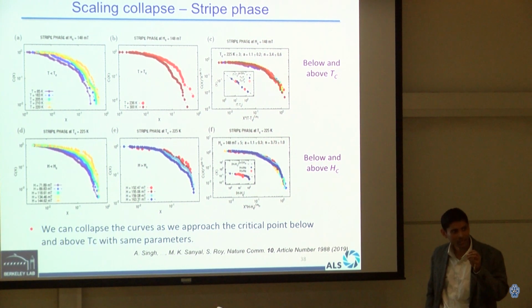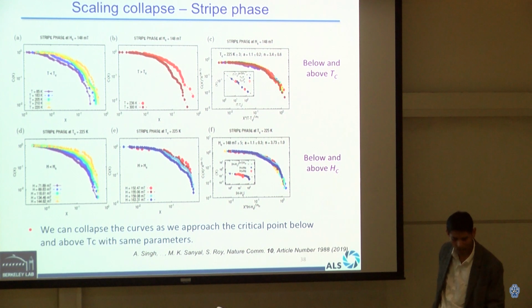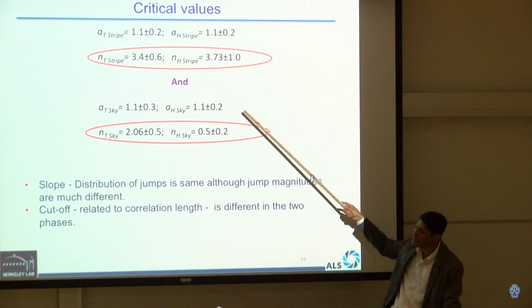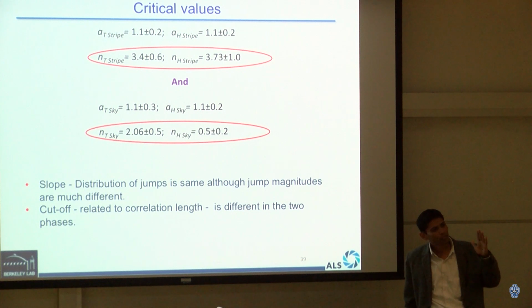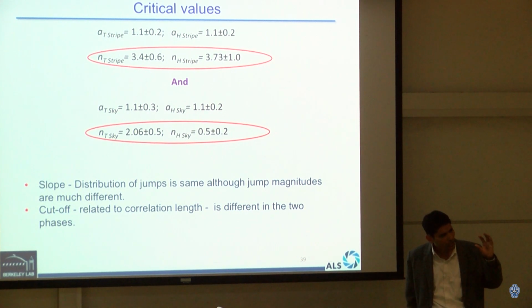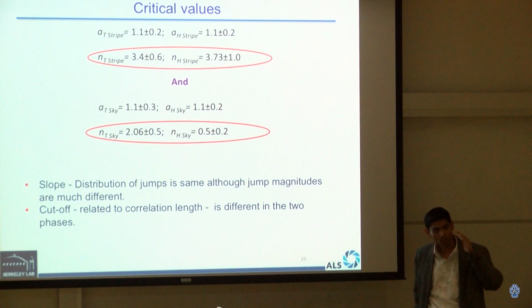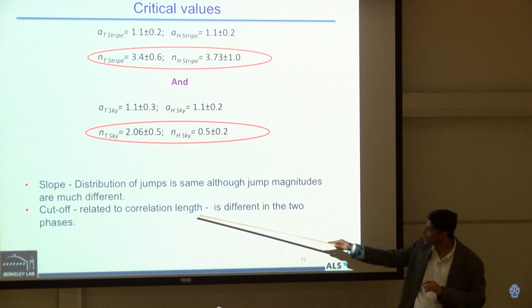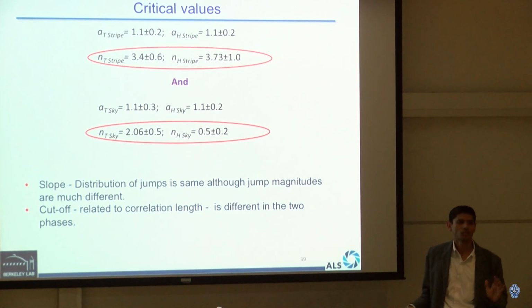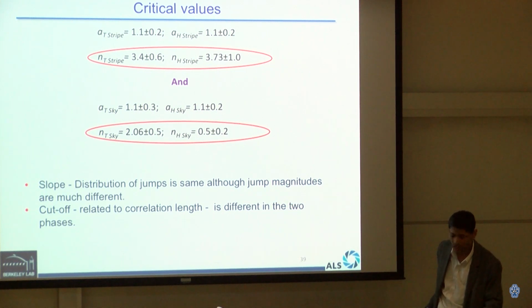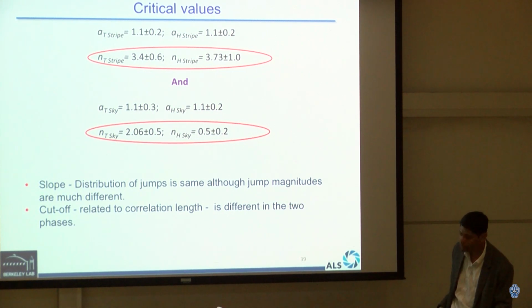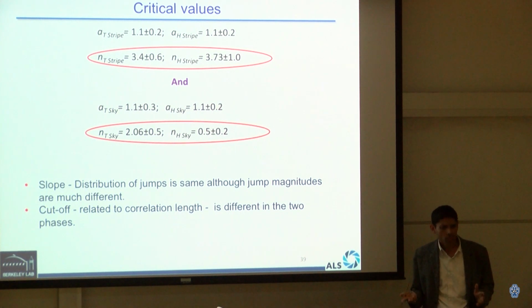From there, you can guess about the uniqueness of a phase. So we did that, and what we showed is that the slope of the skyrmion and the stripe phase are the same, meaning that although there are no jumps in the skyrmion, from a slope point of view, the distribution of the jumps, they may be small, but the distribution is the same. Whereas the cutoff, which is related to the correlation length, they are very, very different. That means that the stripes, at least together, have a lesser phase coherence than the skyrmions themselves. So that was a nice study. This is done mostly by Arnab and a lot of help from James. So that's where we are with our skyrmion.